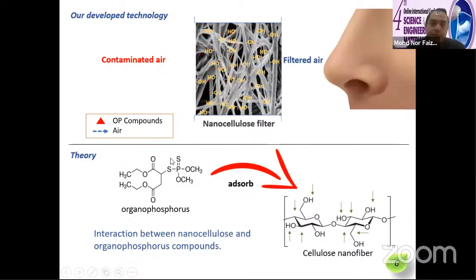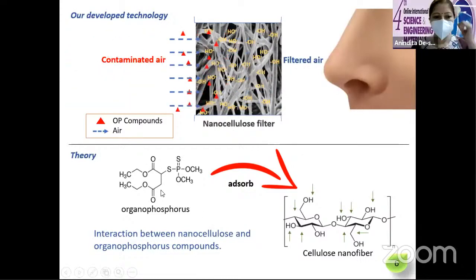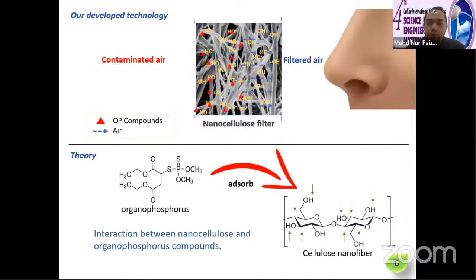To avoid the penetration of organophosphorus. And based on the theory that we try to share here, we can see the chemical structures of these two compounds, organophosphorus and cellulose nanofiber. Nanocellulose has an abundant amount of hydroxyl groups, and organophosphorus has alkyl and carbonyl groups. These are very beneficial for forming chemical interactions, which I will show in the next slide, on how it can interact with nanocellulose.